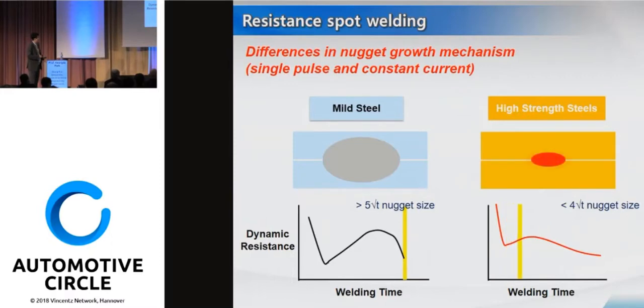Actually, you have a very fast nugget growth, but at the later stage, no more nugget growth here. That's why you have a lot of small nuggets in very high-strength steel. Obviously, if you use very excessive high electrode force, then you can increase further than in here, but this is the kind of limitation. If you grow this nugget very fast, what happens is that at each edge of the corona bond area, there will be sheet separation. So there's no space you can grow the nugget in here.